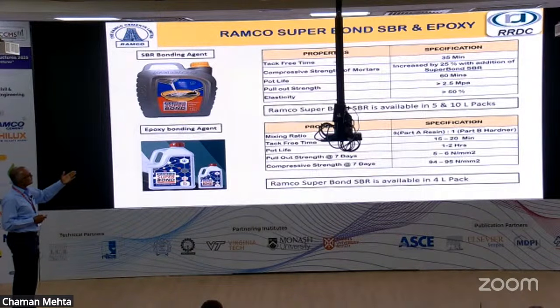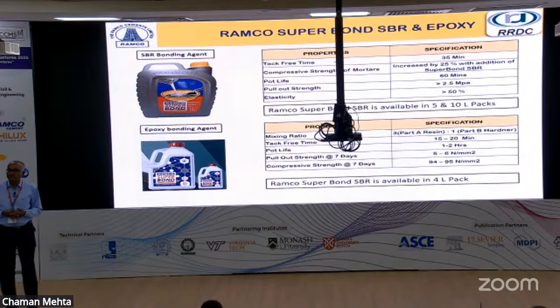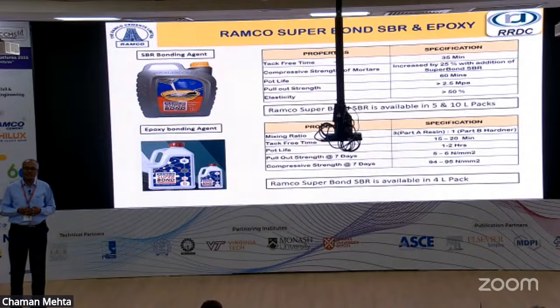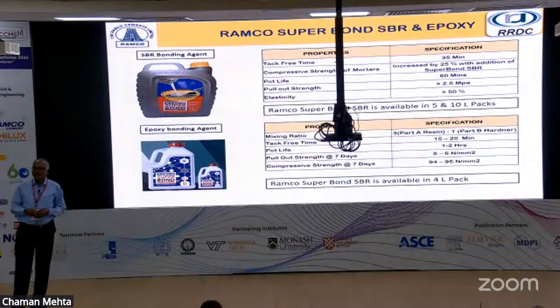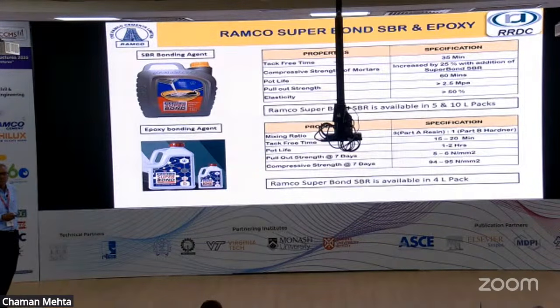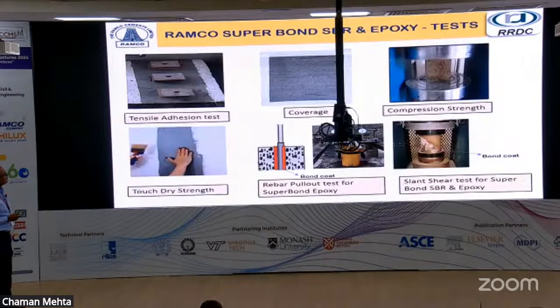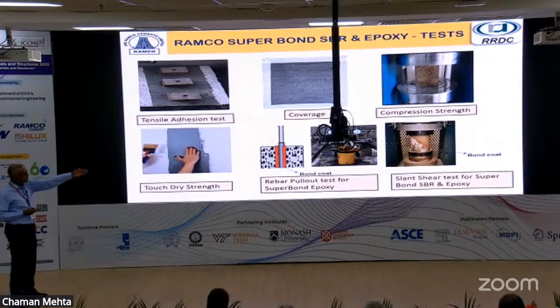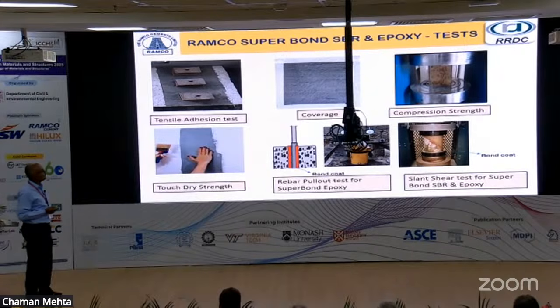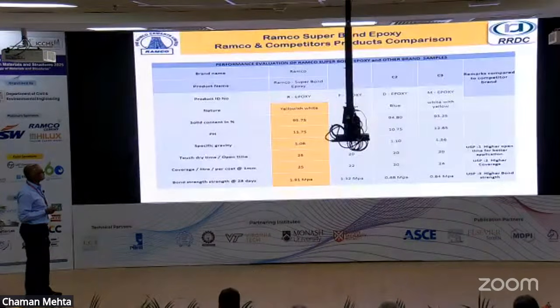Then the super bond and epoxy, both. Of course, the primary objective of using this is bonding old concrete with new concrete, but SBR is also being used as a repair mortar, as a mix of that. So for such applications also it is being used. The kind of tests that we do for that: elasticity, pull-out strength, again, for the epoxy bonding agent, tensile adhesion strength, compression strength, rebar pull-out test, slant shear test. So these are the kind of tests that we do for SBR and epoxy.